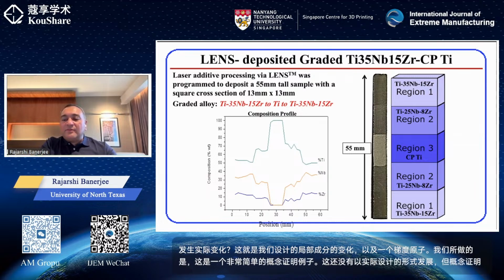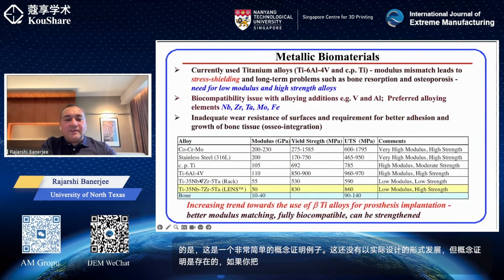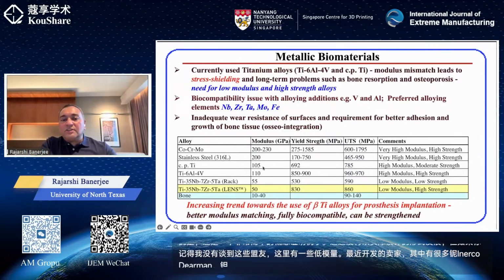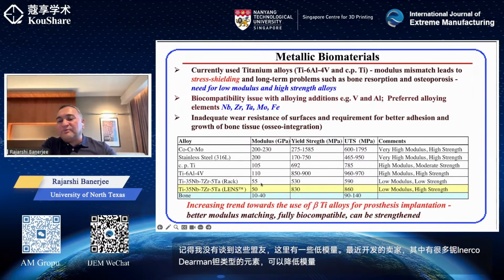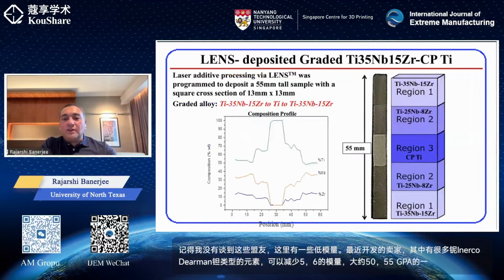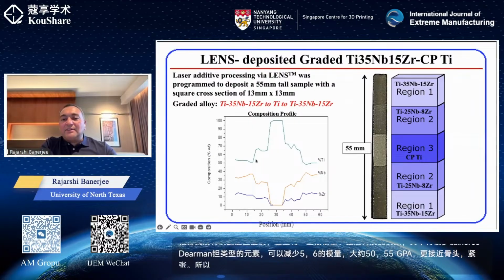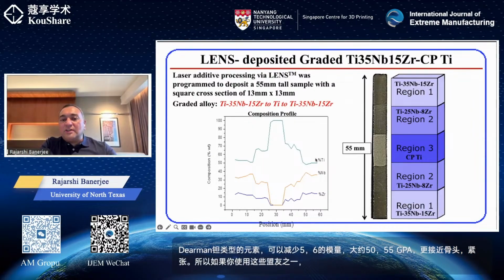If you remember, I didn't talk about these alloys earlier. There are some low modulus alloys that have recently been developed, with a lot of niobium and zirconium and tantalum type elements, which can reduce the modulus of Ti64 to almost half of it, so about 50, 55 GPa, much closer to the bone modulus. So if you use one of those alloys and make that towards the edges, which is the low modulus, we grade the modulus with composition.